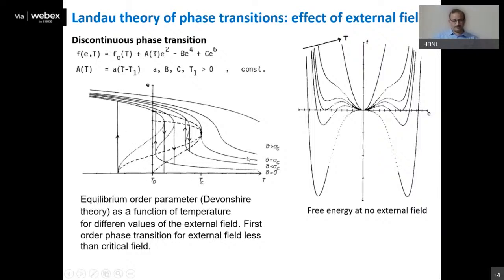Now what happens when we apply a field, but still the field is less than some critical value? In this case, you get this kind of curve, which has some instability region, which is represented by this dotted line. This is similar to the PV isotherm in the liquid gas transition, where we have some instability points and we have some spinodal regions or metastable regions. In this case, again, it will be first order, but the hysteresis will be smaller. And as you go on increasing the field value, you can reach a point where the phase transition becomes second order. There is a continuous transition. So you reach a critical point. So in first order phase transitions, you can have a critical point at some external parameter value.